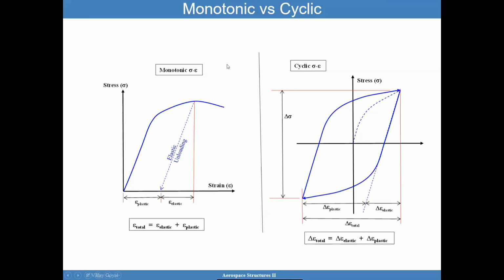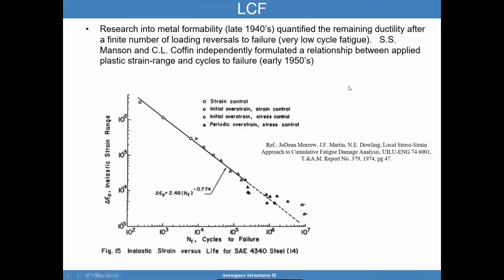Again, monotonic, apply the loading, unload. But here you're going cyclic, and so you go tension, and then you compress the sample, and you're following this curve now. And then you bring it back in tension, and then you continue to collect the data. What people have found, and Manson and Coffin both independently formulated this in the 1940s and 50s, is that it does follow some sort of relationship.